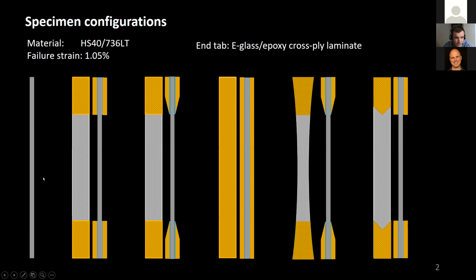So we used the default approach, where you don't have any end tabs. You use just the normal end tabs with the 90-degree corner essentially here. Then we had the tapered design, which some people believe gets you slightly better results than with the 90-degree corner here. Then we used the continuous end tab design developed by Michael. We did something similar with the butterfly design as was presented by Lars.